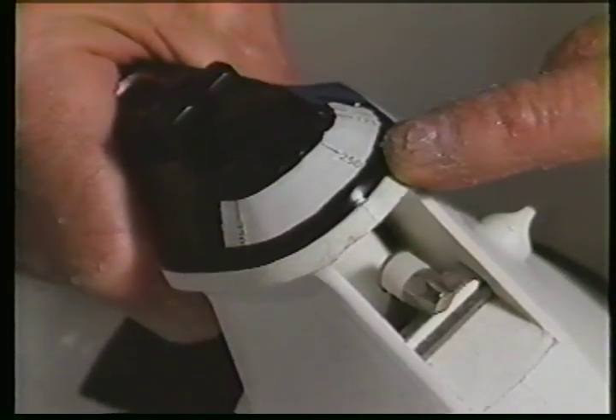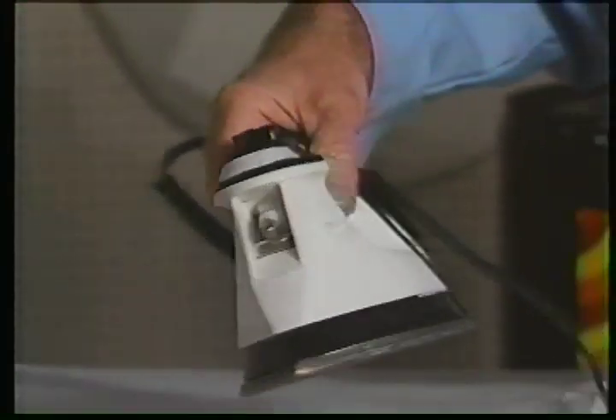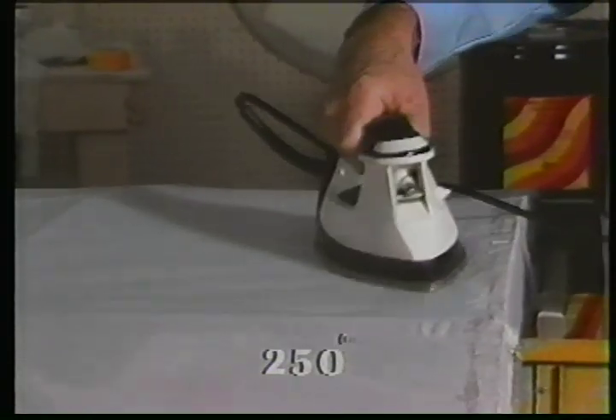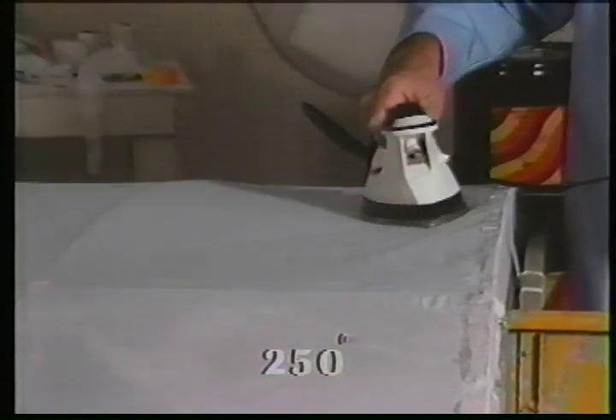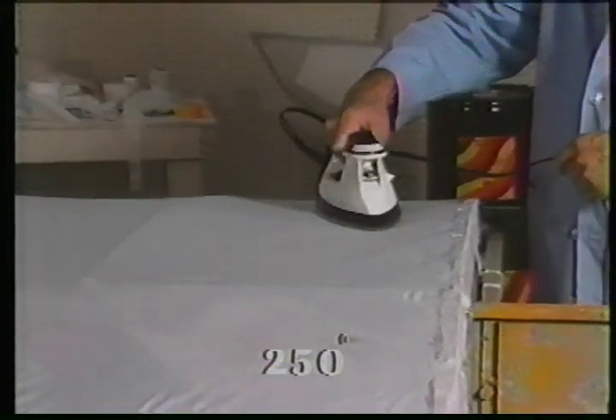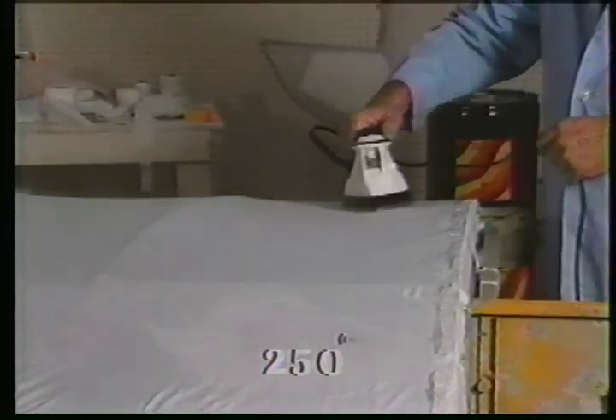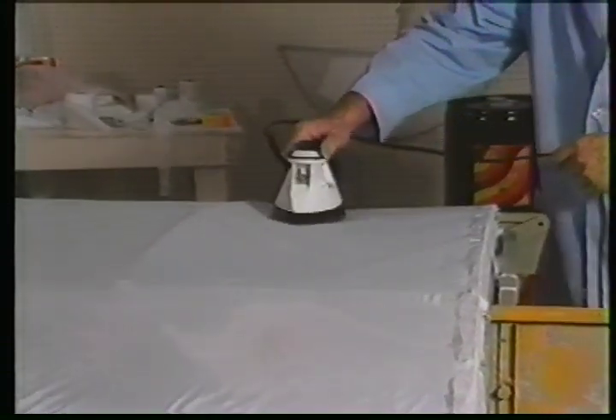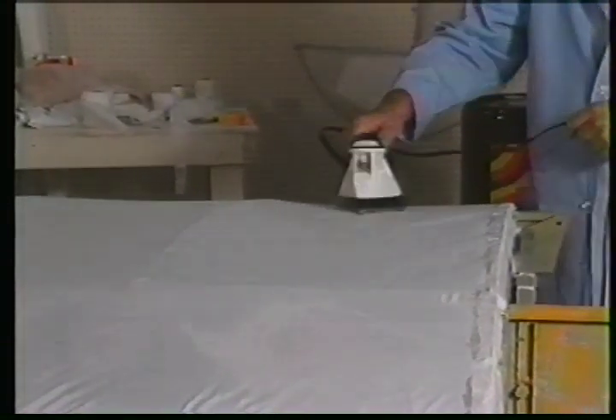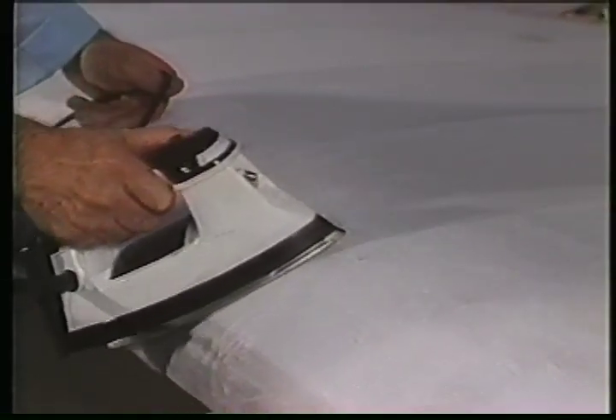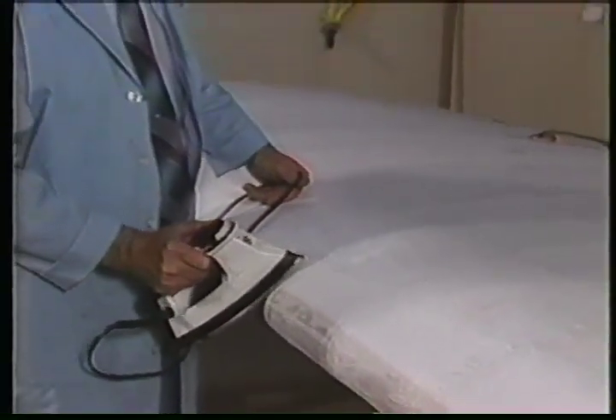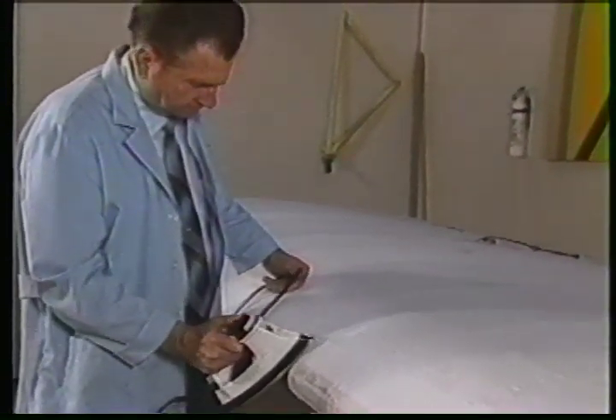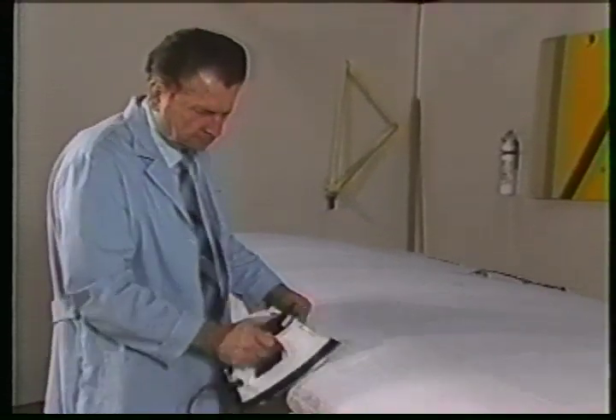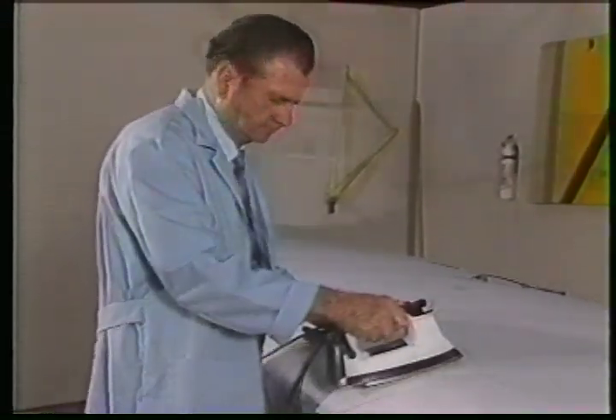The shrinking procedure is accomplished by moving the iron set at 250 degrees temperature in light contact with the fabric surface at 4 to 7 inches per second. A faster speed will not transfer sufficient heat, and a slower speed would be unnecessarily time-consuming. Do not attempt to remove all wrinkles from one area before going to the next. The iron should be passed briefly across each panel area and wrinkles removed uniformly. Several passes at 250 degrees are recommended, working briefly in each area.